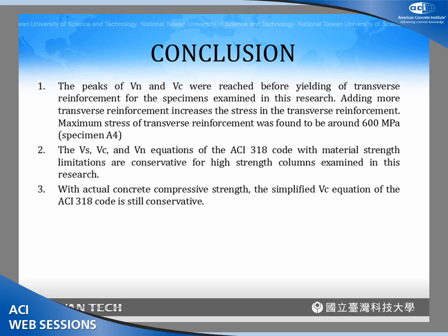So the conclusion, first one, we found that the peaks of the total shear strength and the shear strength from concrete were reached before the yielding of transverse reinforcement. And if you add more transverse reinforcement, the stress in the transverse reinforcement can be increased. The maximum stress measured, I should say estimated, from our specimen was around 600 MPa. If you put more transverse reinforcement, reducing the spacing from 260 millimeter to maybe 130, possibly you can further increase this one, maybe up to yield, but without test data, I cannot make this conclusion.